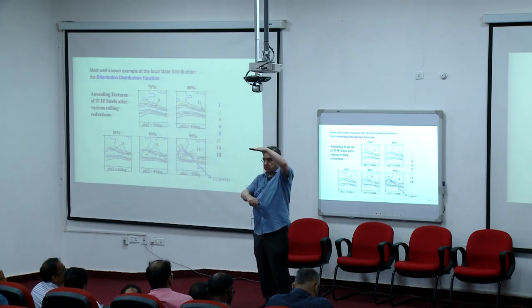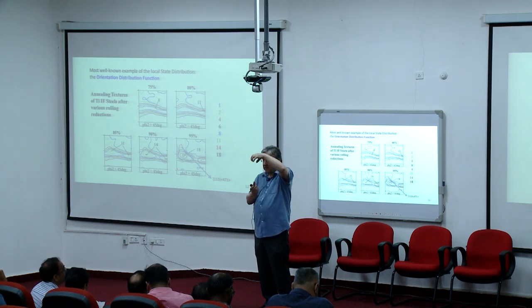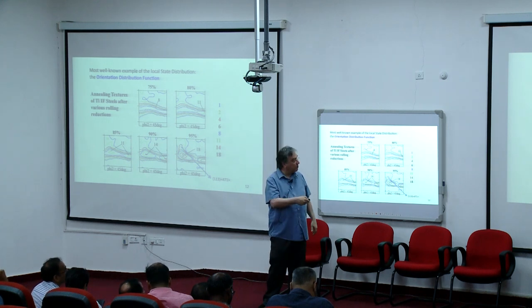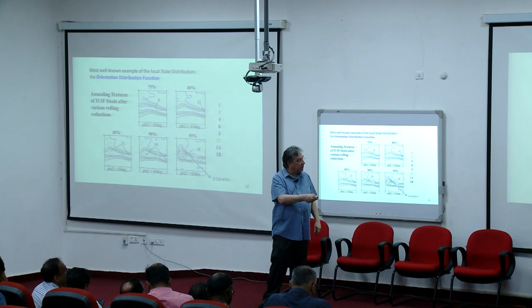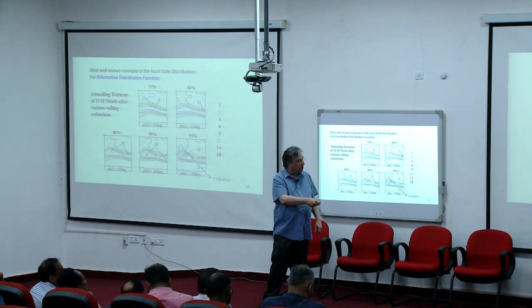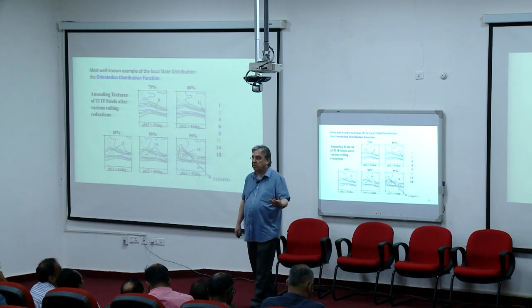that you can make cups with a high limiting drawing ratio, this is called, but also that you don't have ears. And actually, the earing behavior scales with the intensity distribution along this fiber. You can see this is very good. This is much worse, because here you have a maximum. So if you deep draw this steel, you will have a strong earing behavior. If you deep draw this steel, you will have close to no earing behavior.